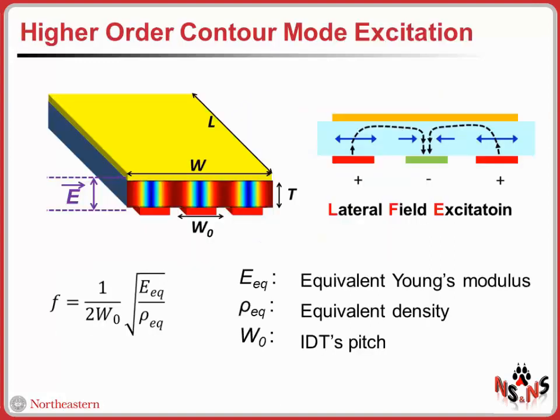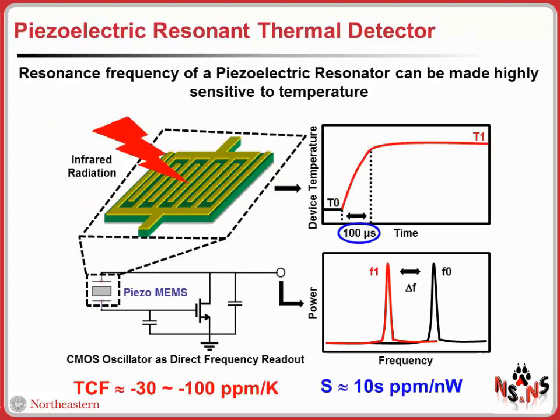Now, by properly patterning the electrodes of the device using this interdigital configuration, it's possible to excite a higher mode of vibration in the mechanical structure. And in this case, the operating frequency of the resonator for a given material stack is set by the pitch of the interdigital electrode. Now the working principle of an infrared detector based on a piezoelectric resonator like the one that I showed you before really relies on the fact that the resonant frequency of these piezoelectric electromechanical resonators is highly sensitive to temperature. These devices are characterized by a temperature coefficient of frequency in the order of -30 to -100 ppm per Kelvin. So very high temperature sensitivity.